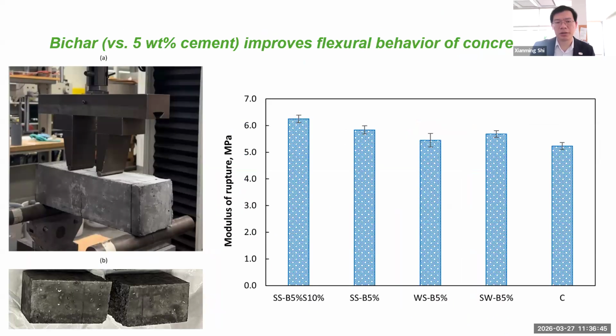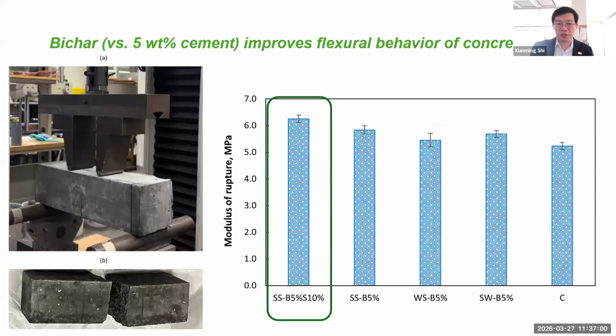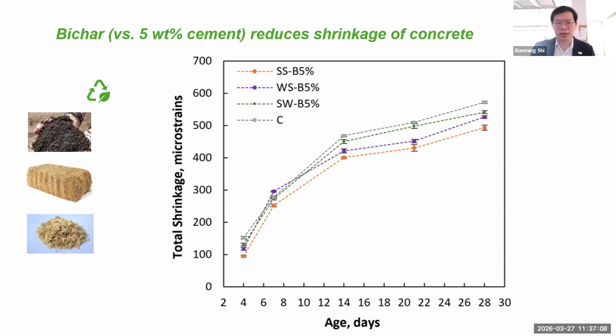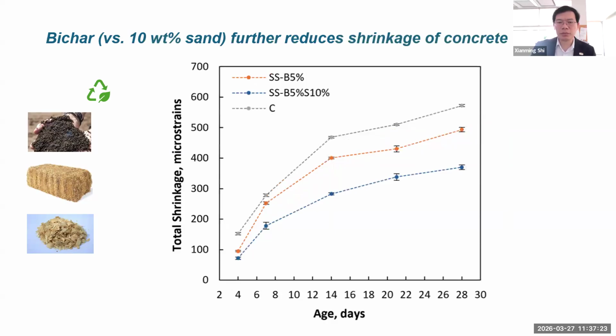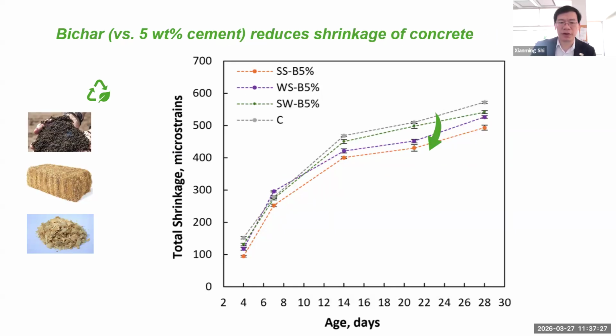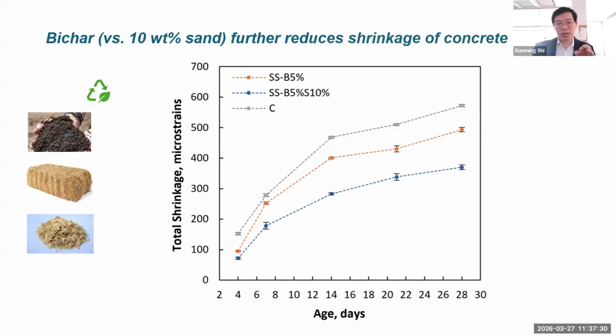Now, we also demonstrate at 5% replacement level, the use of biochar actually significantly improved the flexural behavior of the concrete. Again, flexural behavior is pretty important in many of the use case scenarios, so that's really good news. Now, we also found that the use of this biochar to replace 5% of cement reduced shrinkage of concrete. Again, yet another win, because shrinkage-induced cracking is a concern for the durability of concrete in many cases. Now, here's another one. If we further not just replace 5% of cement, but also replace another 10% of sand, the shrinkage further reduces. So again, it's all good news to this point, right?